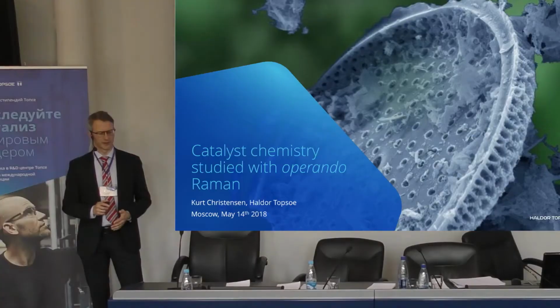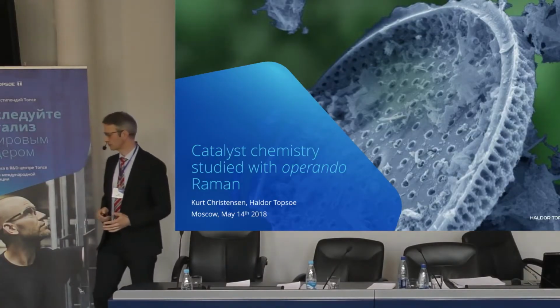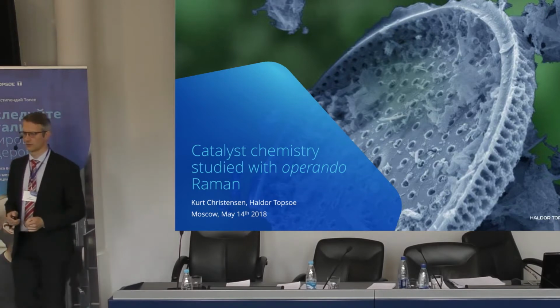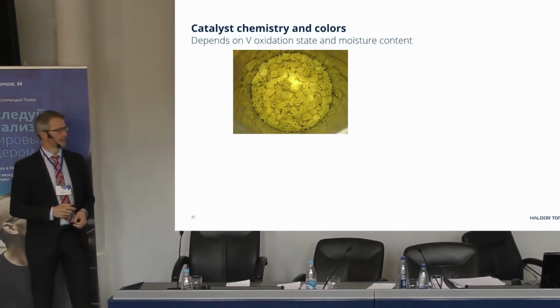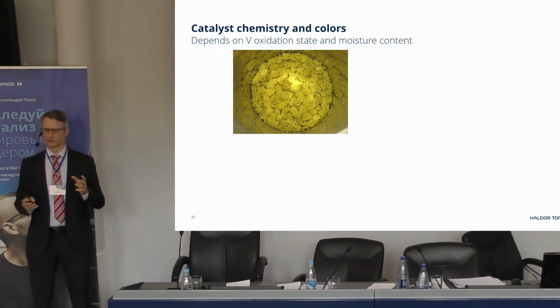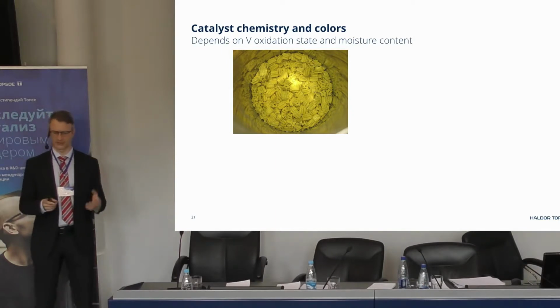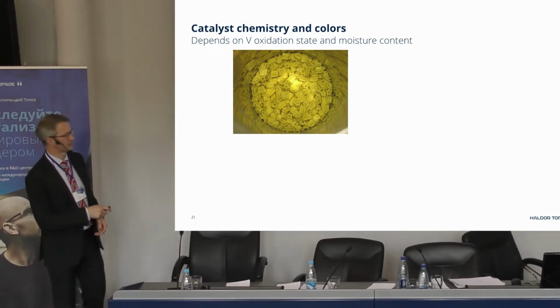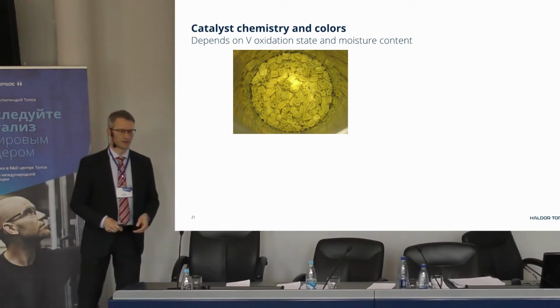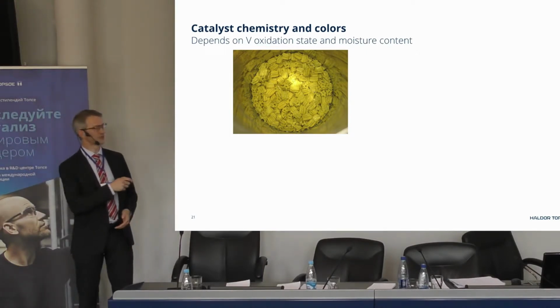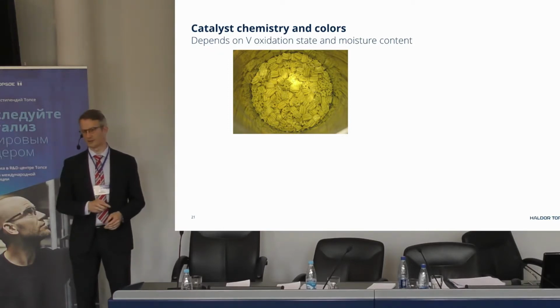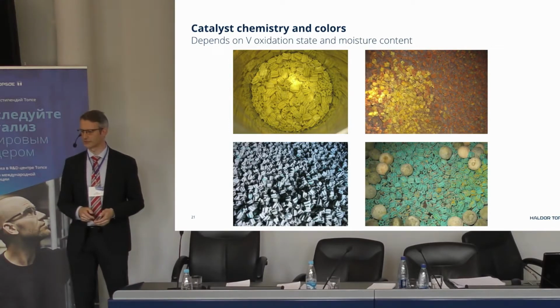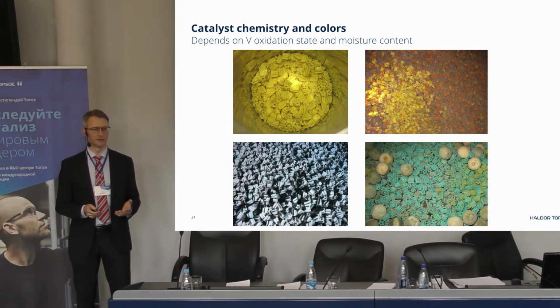Let's move from the physical characterization to the chemistry, and here we are using a unique technique we've developed on Operando Raman. The chemistry of the catalyst is also expressed in the colors, and vanadium 5 has a nice yellow color, and this is what people in industry also like to see. However, a lot of other colors can be found for vanadium species, especially when it's reduced to vanadium 4. You can see green and blue colors.